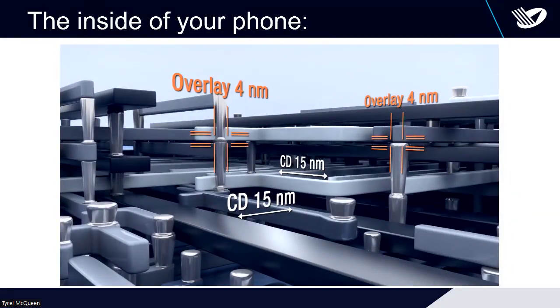How many silicon atoms are that? 4 nanometers. What do you think about that? Yeah, so this is only how much the overlay is in typical chips. So the accuracy you need to reach in the processing is then typically 1/3 of that. So we're talking about 10 silicon atoms with the precision that this needs to be printed across a wafer. That is 30 centimeter, which is 12 inch. Yes. So this is the insane accuracy that is needed here. And that you need to keep in mind. We now need to have metrology tools that verify at every single step that this is working.